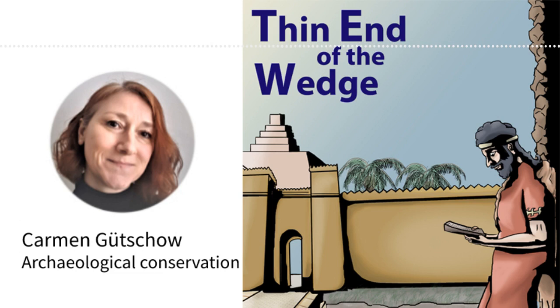What is sinter? Sinter forms over a period of time on surfaces and is a certain leaching mineral like calcium carbonate. Ceramic is often covered by sinter crusts, but also stone and metal objects. Those calcareous crusts can be softened and removed by acids like citric acid or acetic acid. The artifacts can be bathed in a low concentration or you can make a compress. Important is to neutralize the acid by washing or compresses at the end, otherwise you risk that the remains of the acid will damage the artifacts after a while. It's fiddly and time consuming, but it's worth it.